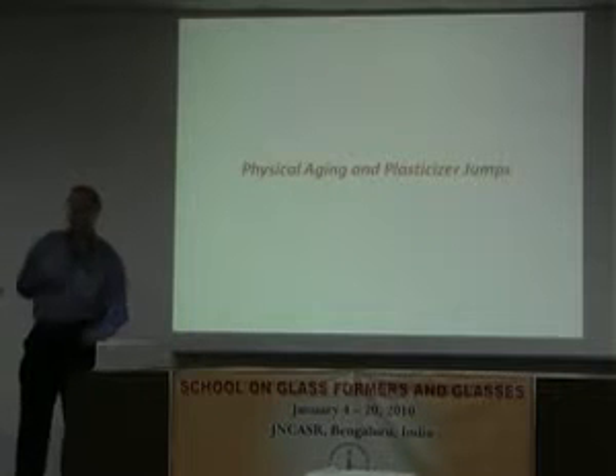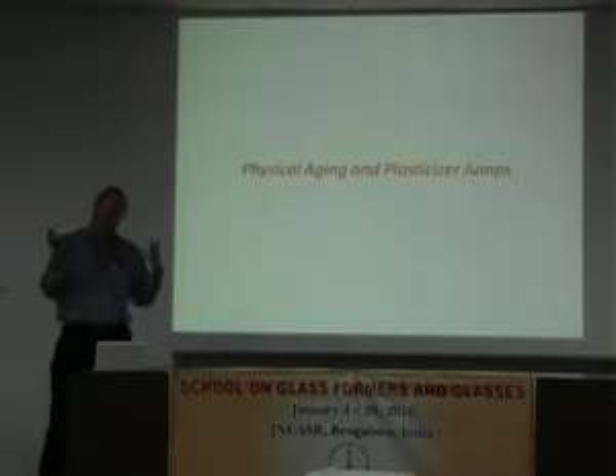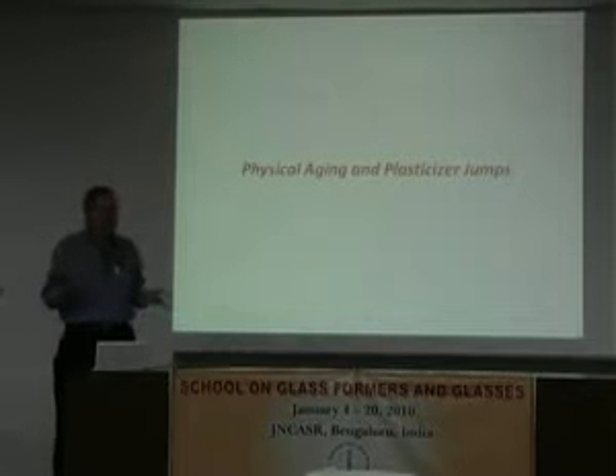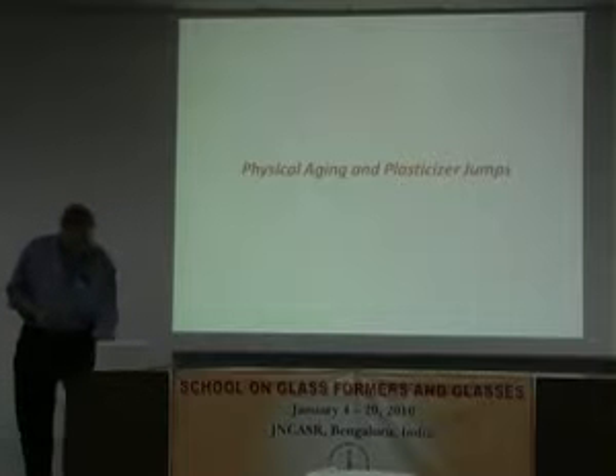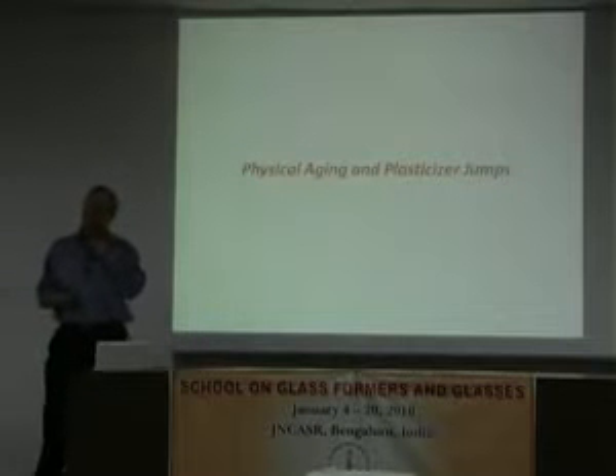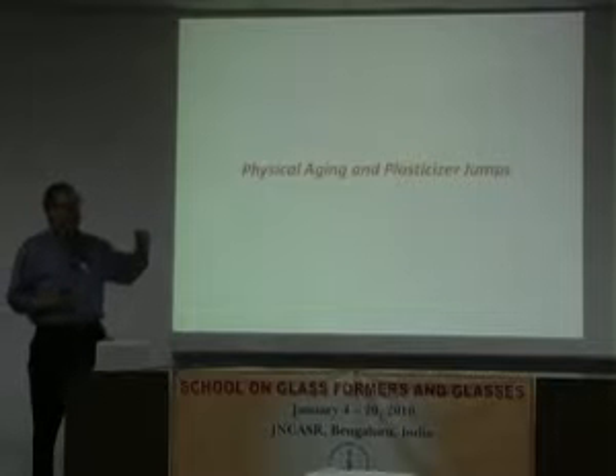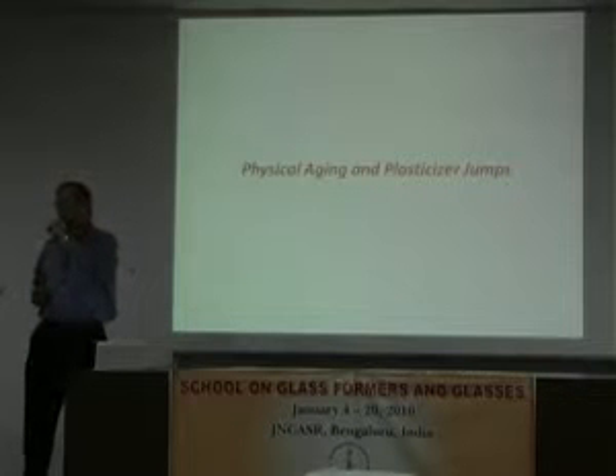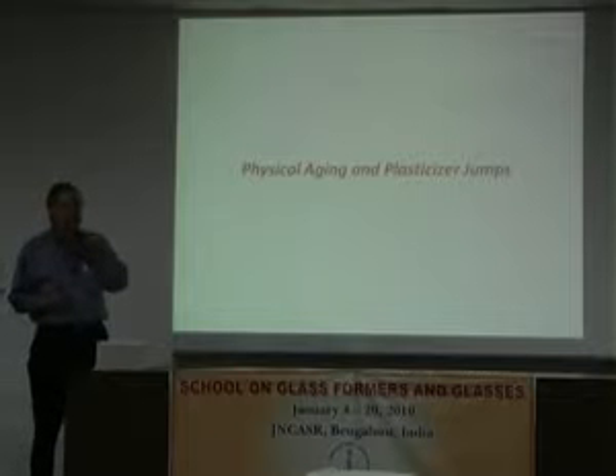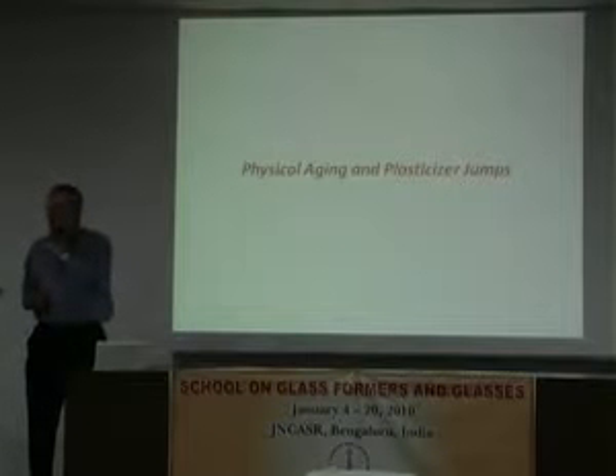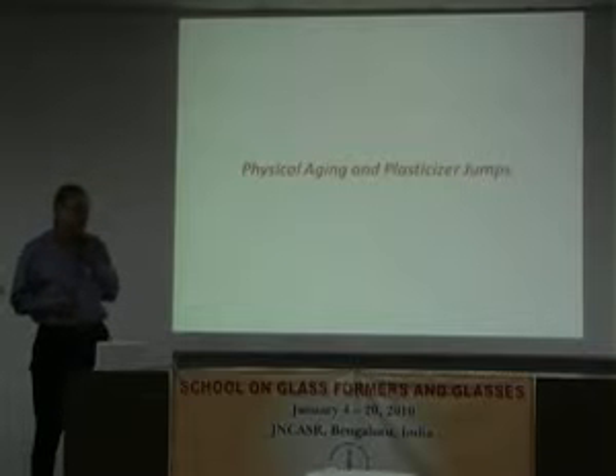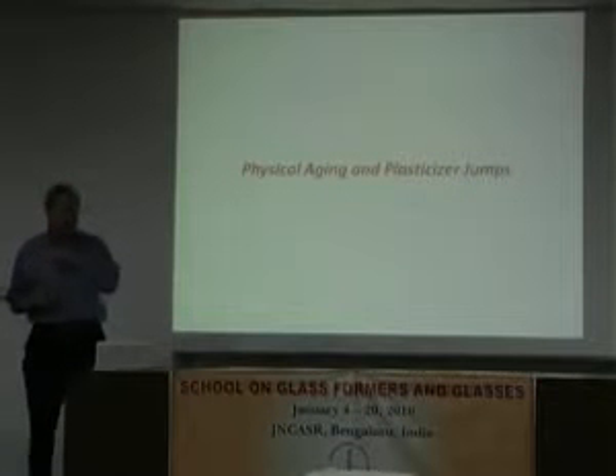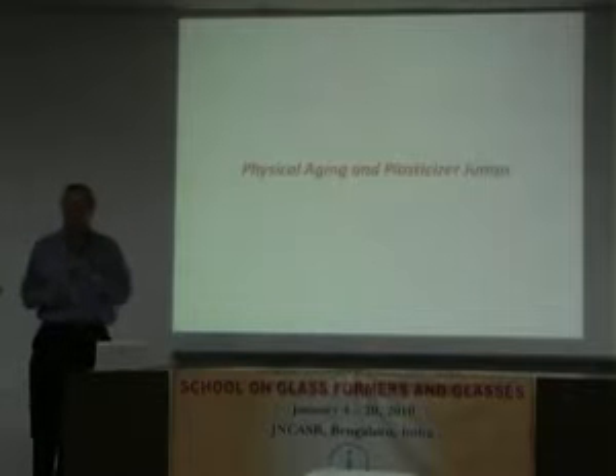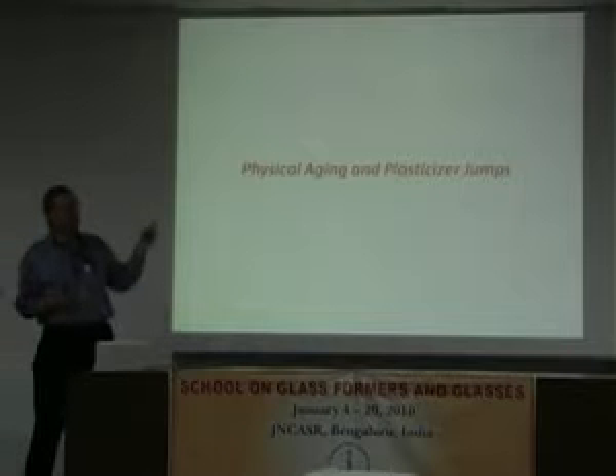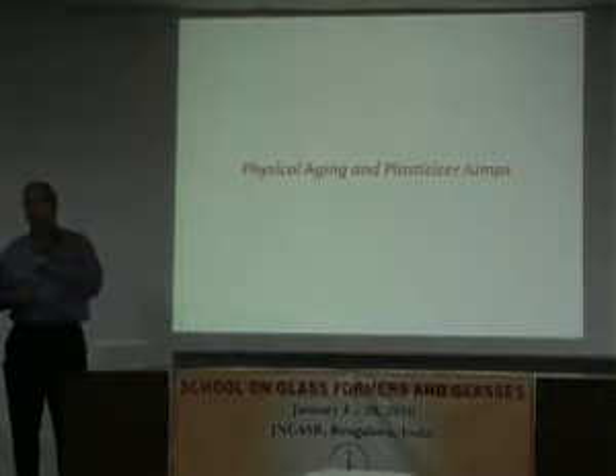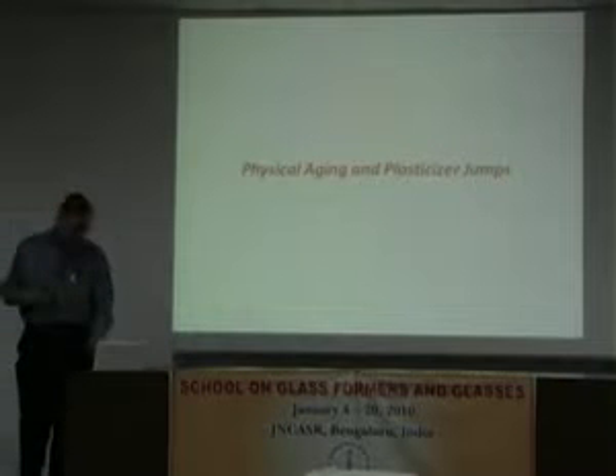Okay, so now I'm going to show you that we get the same thing with the plasticizer jumps, just like we saw qualitatively. And this leads to an understanding that even in the plasticizer jump case, even though the rates of relaxation are not the same in the structural recovery, I still get aging time superposition, or time-structure superposition, even though the structures seem to be different. So the details of the structure don't seem to be what's determining this time-structure superposition, but they do determine the magnitude of the relaxation times.